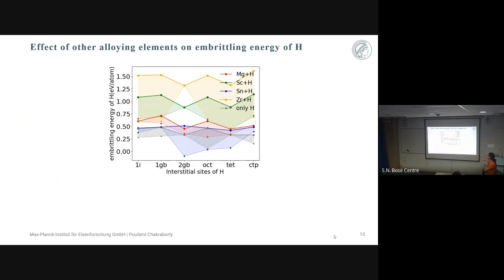However, for the blue curve and the gray or black curve, you see something interesting, right? The blue corresponds to tin atoms, and the black curve is where there are no solute elements present. So we see that when we consider the lower limit of tin atoms, the embrittling energy is becoming much lower. It is an extremely interesting effect. Why? Because that means that the embrittling tendency of hydrogen is somehow decreased by the presence of tin atoms.